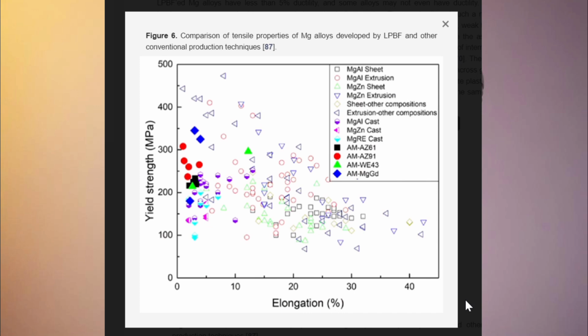Yield strength versus elongation. But when comparing LPBF fabricated magnesium alloys to their cast and wrought, whether rolled or extruded, counterparts, a significant difference in yield strength emerges. So you can infer it from figure 6. Typical magnesium alloys designed for structural application generally have a yield strength exceeding 200 megapascal, with some reaching up even to 350 megapascal. However, despite their strength, LPBF magnesium alloys often exhibit extremely low ductility, usually below 5%, and in some cases they lack ductility altogether.